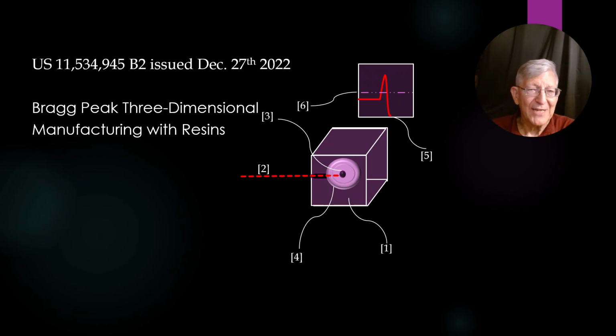What our patent entails, this was actually from December of 2022, these are drawings from that patent application. If you had a medium, and we're using liquid resins, that would be number 1 in this scheme, and you fired a proton beam, that would be number 2 in this scheme, into that medium. That proton would slow down and at some point would come to the point where you're approaching 0 velocity. The linear energy transfer would skyrocket as indicated in the graphic above.